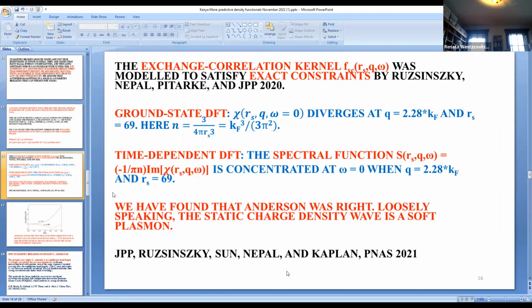And from where the response function diverges, that means that the uniform phase is unstable against the formation of a charge density wave, because it means that the uniform phase will have a finite response to an infinitesimal perturbation, which means that it will spontaneously form a charge density wave.